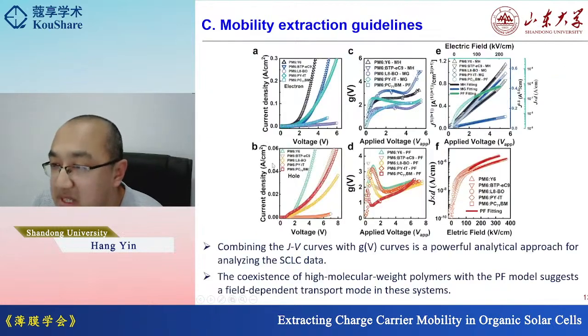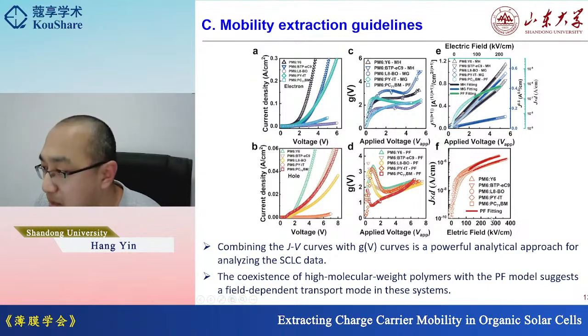And then we just take the PM6 based BHJ systems with various acceptors as examples, and we just combine the JV curves with the g(V) curves. We observe it's really a powerful analysis approach for analyzing the SCLC data. And we can conclude the coexistence of the high molecular weight polymers with the PF effect suggests a field-dependent transport model in these systems. That's the same for the hole transport.